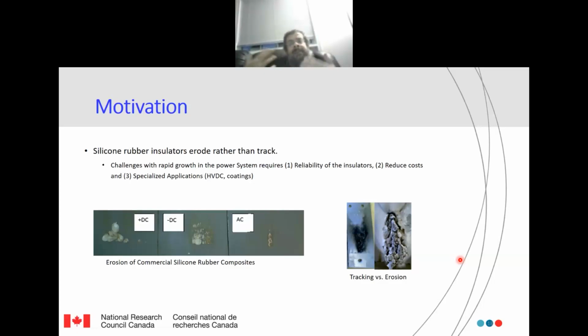And this makes some more challenges on the design of the material. So these are some research done at the NRC trying to test different fillers under AC and under DC as well. And you can see here the erosion under DC is more severe. Why? Because in DC, we have only a single polarity.